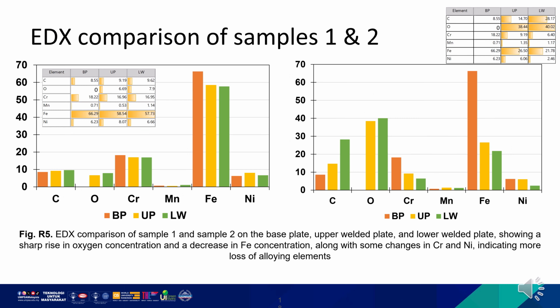So comparing sample number 1 and sample number 2 EDX, sample number 1 maintained better composition control with only slight chromium nickel depletion and minimal oxygen uptake. But sample number 2 suffered severe oxidation, high O2 levels, a significant amount of nickel loss and greater chromium depletion. Elemental redistribution was more pronounced in sample 2 than in sample 1. It shows that the process parameters for sample number 1, lower power and high frequency, might have yielded better oxidation resistance, and that these samples are very sensitive to the laser parameters.